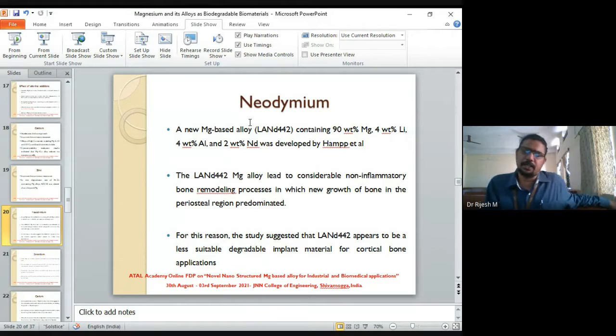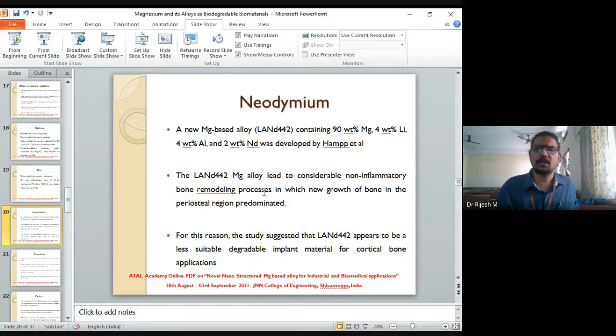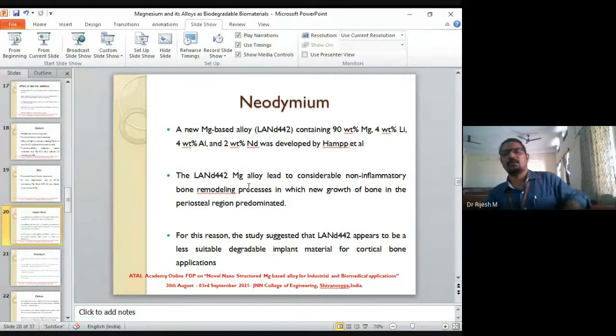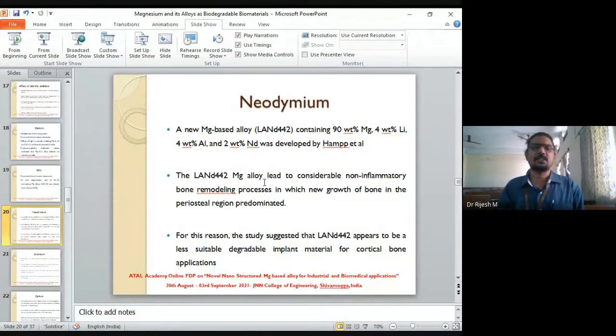Neodymium is one alloying addition that we generally give for magnesium. If you go for alloying additions like 90% magnesium, 4 weight percent lithium, 4 weight percent aluminum, and 2 weight percent neodymium, we found that that led to a considerable non-inflammatory bone remodeling process, in which new bone growth in the periosteal regions predominated. This is not good news. For this reason, the study suggests that this alloy appears to be a less suitable degradable implant material for cortical bone applications. So any alloying addition, if it is not increasing the corrosion resistance, is of no use.